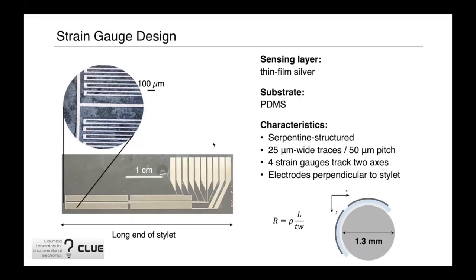So for example, our fabricated device has a total trace length of 16.5 centimeters. The trace metal film thickness is 60 nanometers, and the trace width is 25 microns. So that means each strain gauge has a base resistance of 3.3 kiloohms over a surface area of 14 square millimeters.